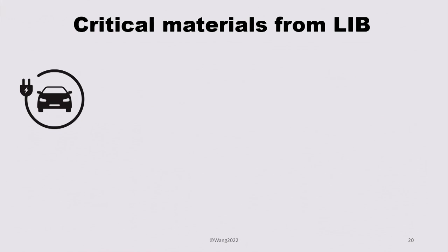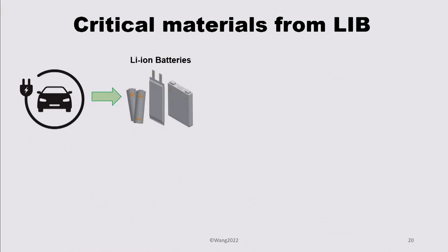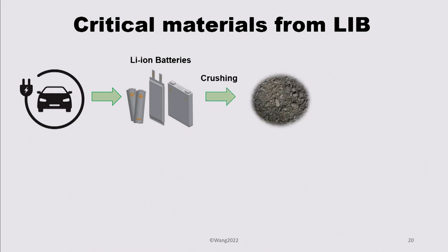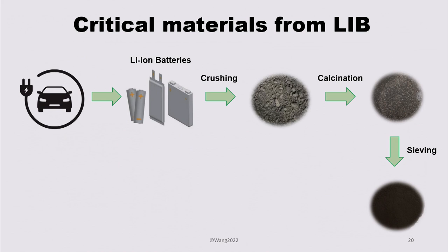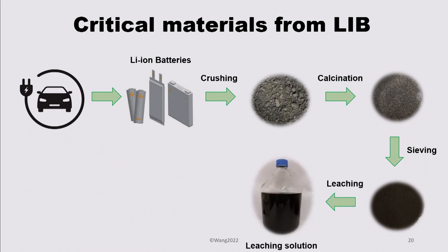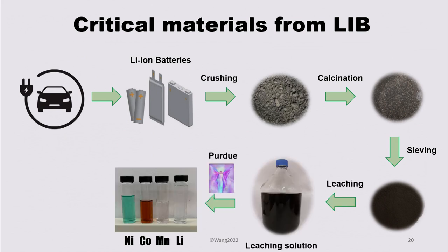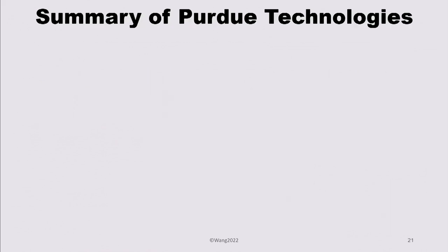We also have done successfully in the lab scale so far the end of life lithium ion batteries. Collect them, crush them, calcinate to remove the binders, sieve them, leach them with a weak acid, and then we use the Purdue methods to purify into nickel, cobalt, manganese, and lithium. So this can be reused into the cathode materials for lithium ion batteries.